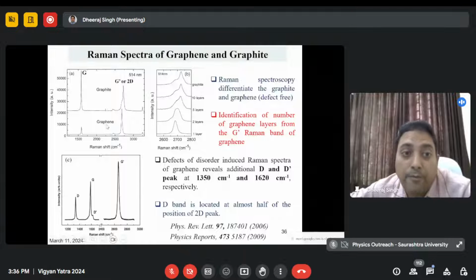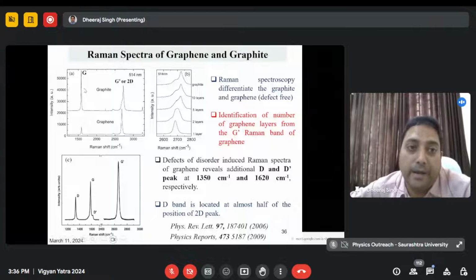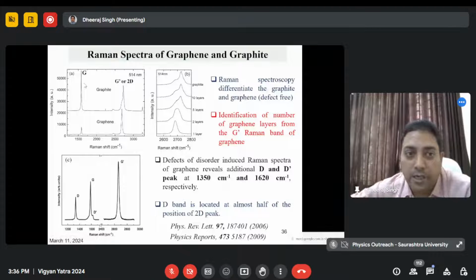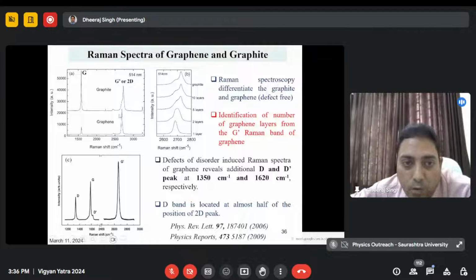In graphene, actually we find a peak, we call it the G band. G band means graphene band, an in-plane C-C stretching mode. In-plane vibration, we call it the G band. If you are getting a peak at 1589, we call it the graphene band. And now we can see how Raman spectra clearly identify graphite and graphene by these two things. In graphite there is a certain doublet, but in graphene only one single peak is there.